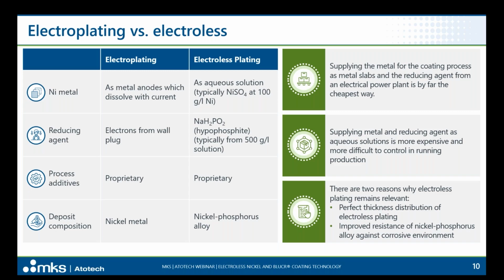It's also important to mention that in case of electroplating, we have a pure nickel metal as deposit, while in case of electroless nickel, we obtain a nickel-phosphorus alloy with very good properties. Nevertheless, the electroplating is by far much cheaper than the electroless technology. At the end, there are two reasons why electroless plating remains relevant. First is the perfect thickness distribution all over the part, also on very complicated shapes, and the improved resistance of the nickel-phosphorus alloy against corrosive environments.